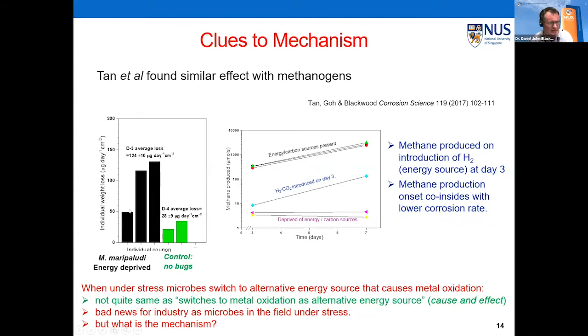And this one here, you see, doesn't seem to be very much higher corrosion rate than the controls. And the reason for that was partway through the experiment, we allowed hydrogen into the system to basically feed the bugs again. One of the things I've always found annoying about bugs is they have this habit of dying on you, and that upsets your experiment. So we weren't sure whether the bugs were alive, so we let some hydrogen into them, and then they start producing methane. And as they start producing methane, because they've got plenty of nutrients, they stop corroding. So it was definitely the bugs under stress.